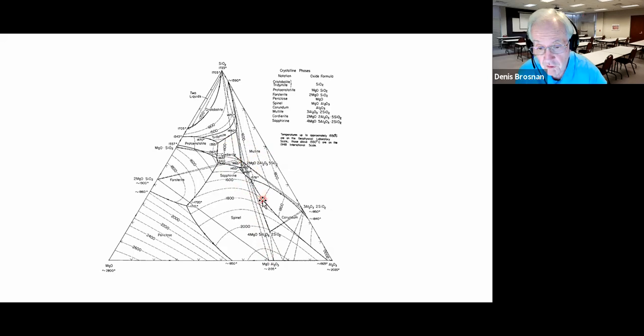If you get off the composition a little bit, then you're going to have other minerals, and they're going to change the thermal expansion coefficient. For example, if we miss the composition and have a lot of free silica, that's going to be the highest possible thermal expansion coefficient. So generally, people that make cordierite like to be over here in the mullite cordierite area. Some of the newer technology suggests that you might like to be in the magnesia spinel cordierite area. But you really don't want to be over here toward MgO or toward enstatite or forsterite, or certainly free silica. So that's the deal.